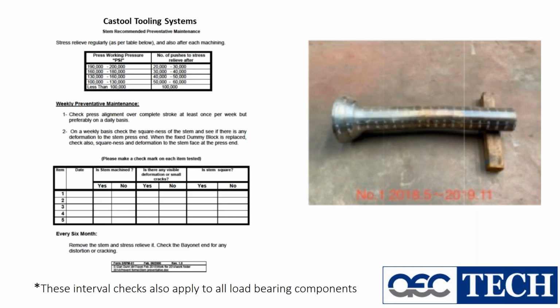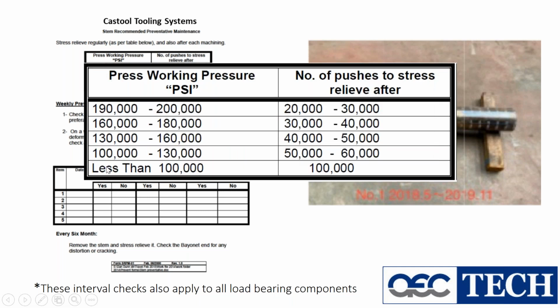There is a calculation for doing that we came up with years ago, and that's based on the column strength of the steel. So we don't see many presses that are over 130,000, but when we put this together, we did this based on a solid piece of steel. So if we look at most presses that are running at less than 100,000 PSI, now that's on the face of the dummy block, not the face of the die.